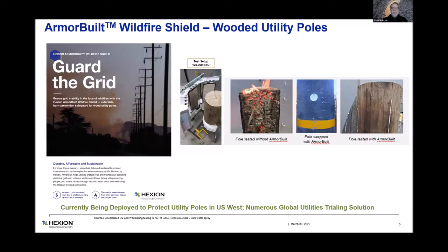ArmorBuilt is an intumescent material that, once it sees the right amount of temperature, starting at about 380 F, expands just like the picture behind me. That is actually a third-party certified test result where the material intumesced and puffed up once it saw about 380 to 400 F. And that went 10 minutes at 2,100 degrees at 9 inches, and it barely sunburns the wood.